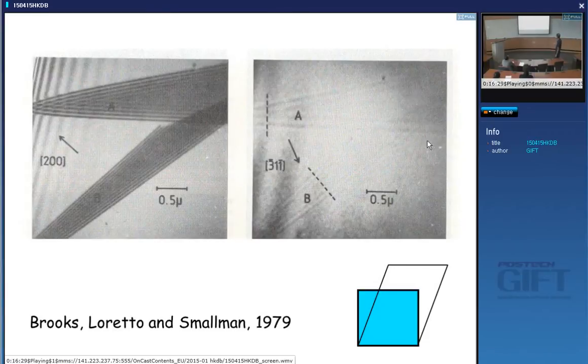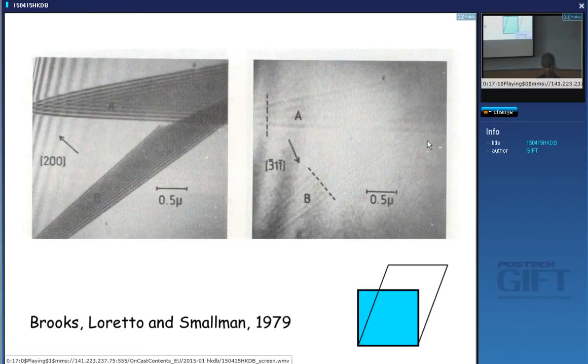And if you change the lattice parameter by alloying, then the volume change will also be different, and this contrast changes. So these people took a series of 3 alloys in which the density difference changes, and demonstrated that the residual contrast here corresponds to what you would expect from different volume changes. Right? So it's brilliant. This is a nucleus of martensite, and it shows that it truly is hexagonal close-packed. It's not just a stacking fault. There's a volume change normal to the fault. Okay?